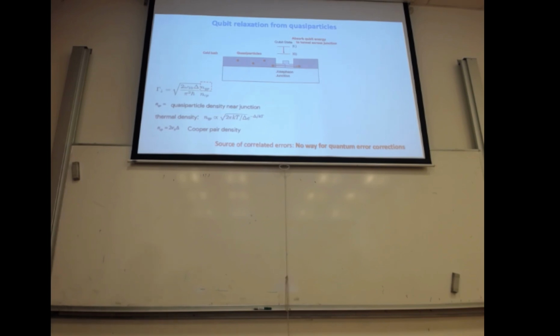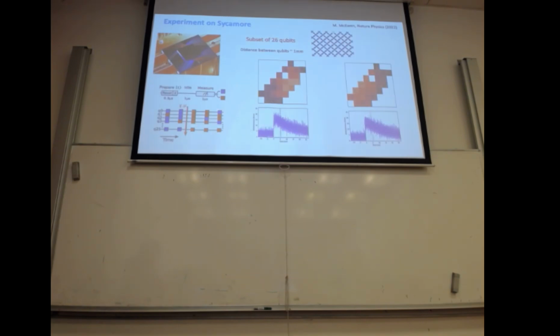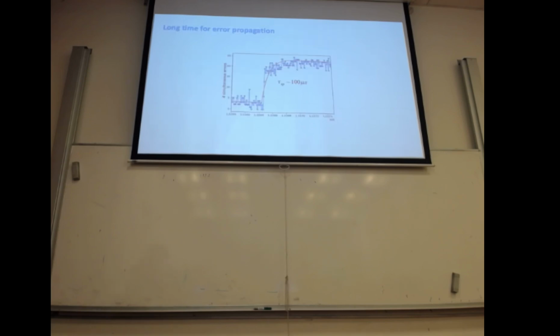But there is an interesting feature that Matt observed, which is that after the cosmic ray, you always see decay. What does it mean? It means that the quasi-particles that arrive here do not have high energy. They are cold, because they always absorb energy from the qubit. They cause gamma 1. They never cause excitation of this qubit. So somehow they arrive and they are cool. And when we saw that, we saw this was the end for error correction. We really needed to solve this problem.